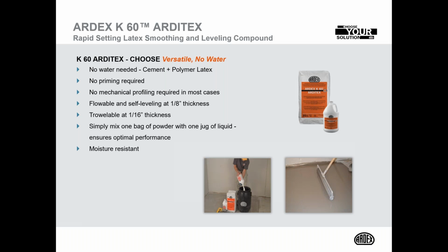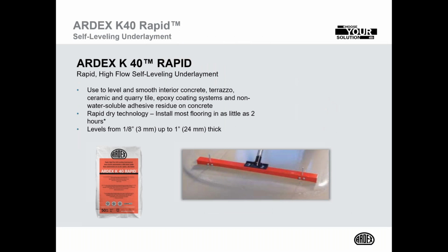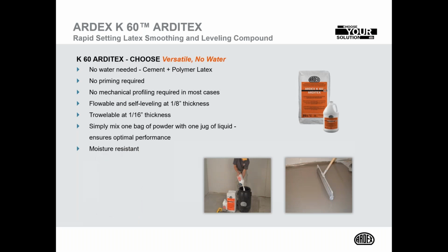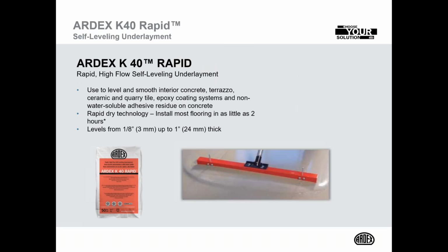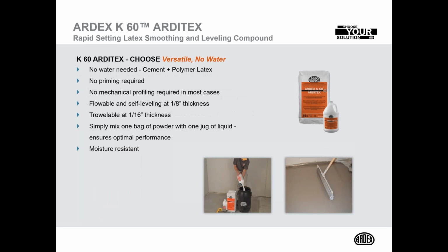There's a lot of powdered goodies in there, and we have the liquid latex. So with the powdered polymers in that bagged product and the liquid polymer in the jug, that enables this product to stick to a variety of different surfaces without a primer. Porcelain tile, which has an absorbency of less than 0.5%. If that surface is clean, the K60 is sticking to the porcelain without any primer.